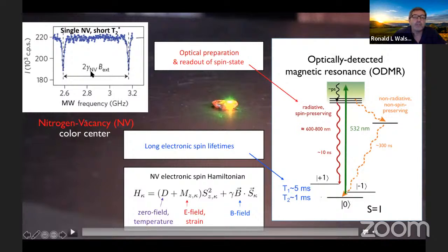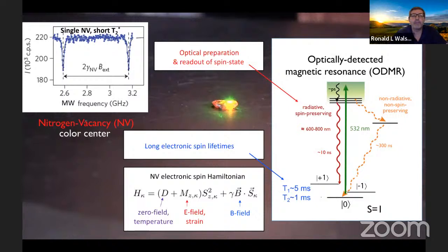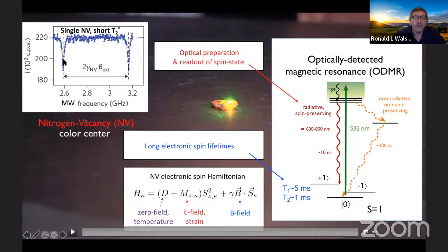And that splitting between the two resonances can give you, because you know the magnitude of the gyromagnetic ratio, gamma NV, the magnitude of the magnetic field that is applied to the NV. And right on, as you sit on the side of the resonances, this very rapid change of fluorescence with static magnetic field or microwaves gives you a sensor of what the magnetic field is.